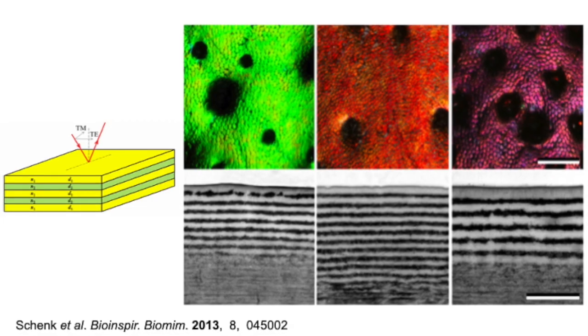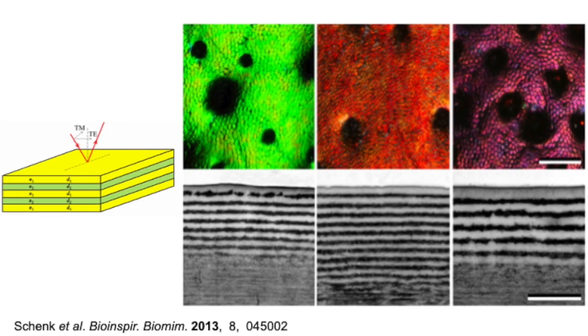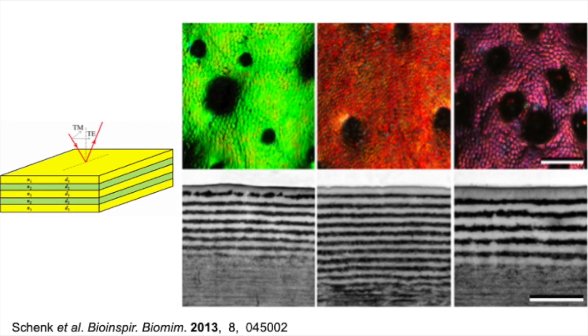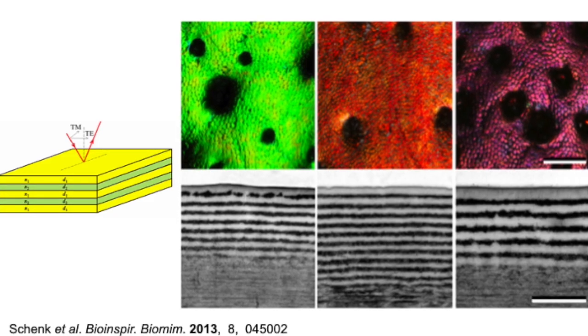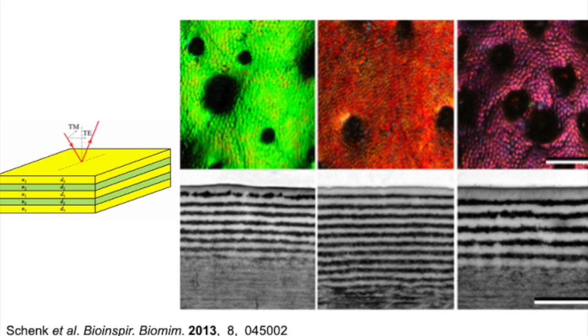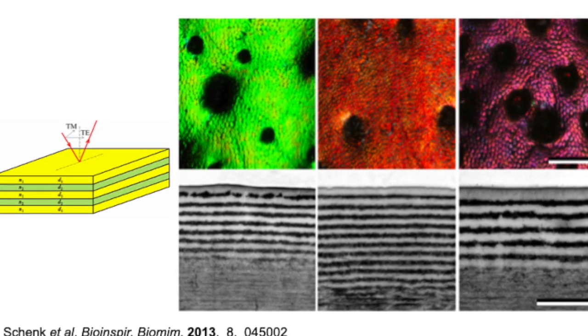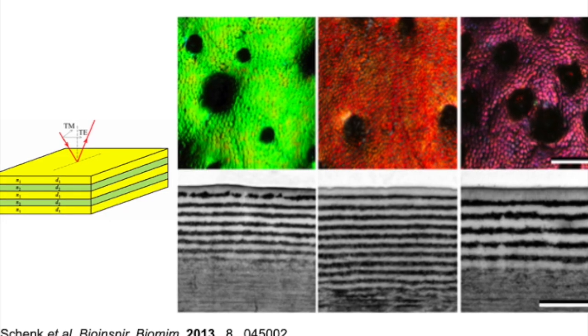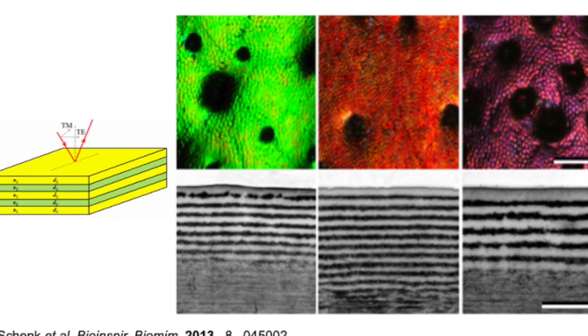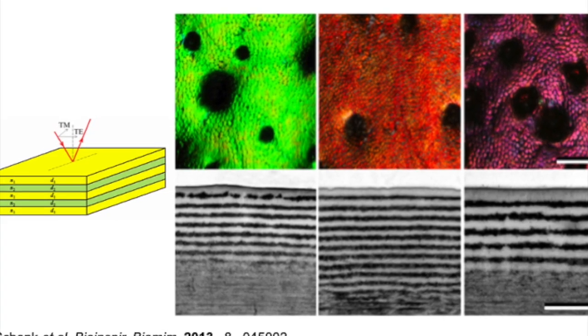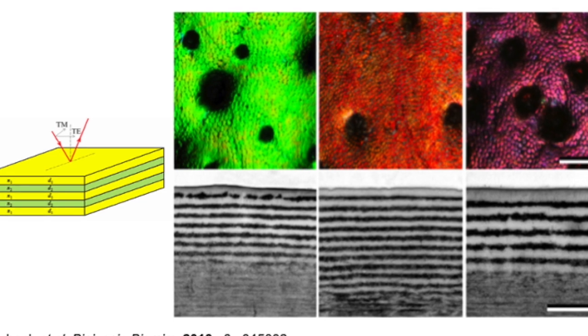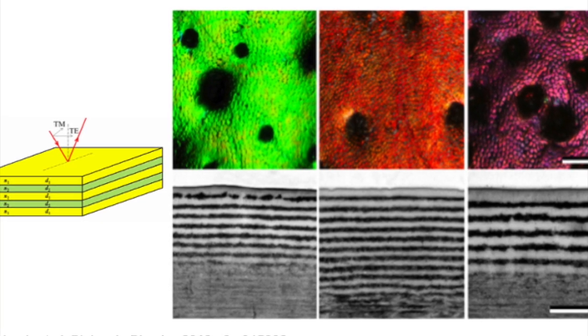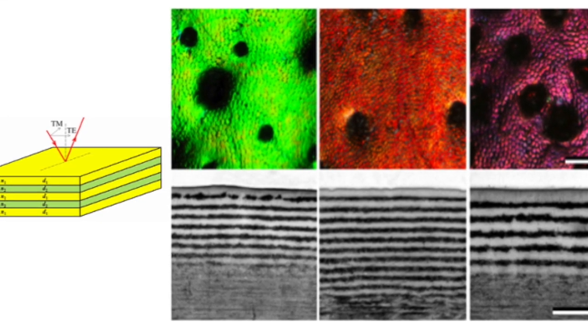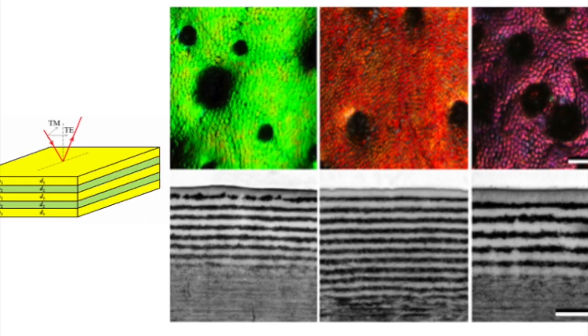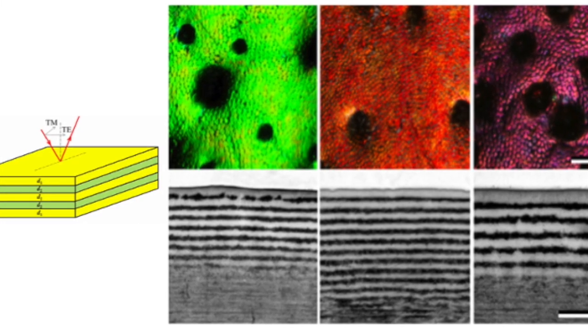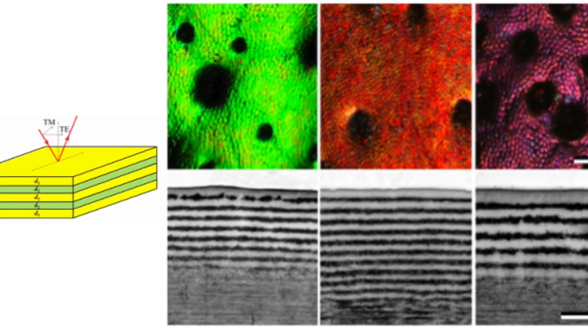The number of layers varies across color regions, with about 16 layers in the green area, 22 in the orange area, and 12 in the purple area. The layers are not discrete, but instead exhibit a graded structure, so the refractive index does not change abruptly from one layer to the next. Rather, the refractive index oscillates between approximately 1.6 and 1.7 with a periodicity that depends on the location.